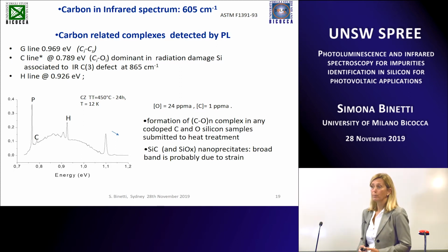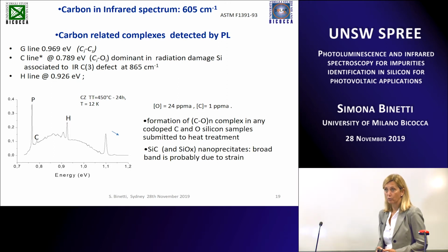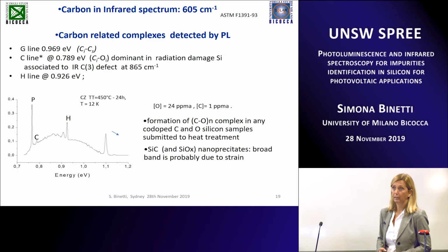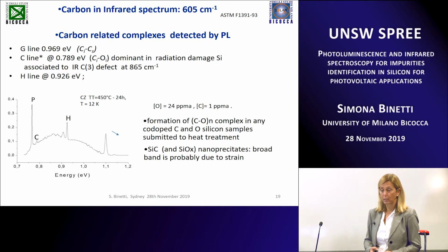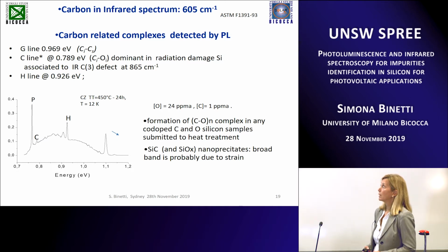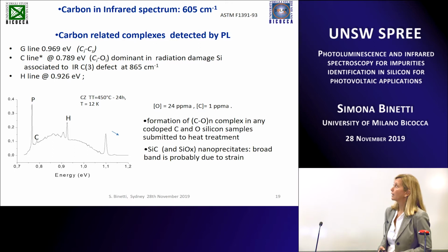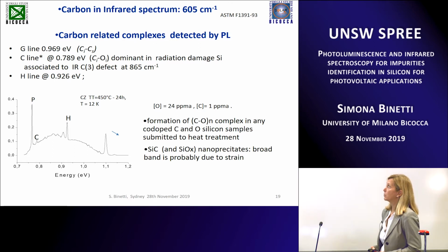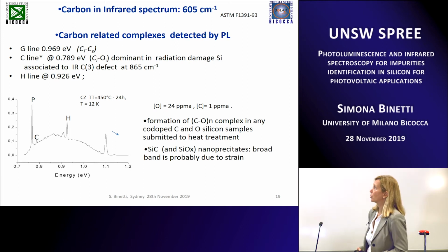Carbon in substitutional position does not introduce a level in the band gap, but in interstitial position it introduces a level in the band gap. So it can be detected by photoluminescence, because it's possible to have the formation of some defect complexes like carbon substitutional and carbon interstitial, or carbon interstitial with oxygen interstitial.